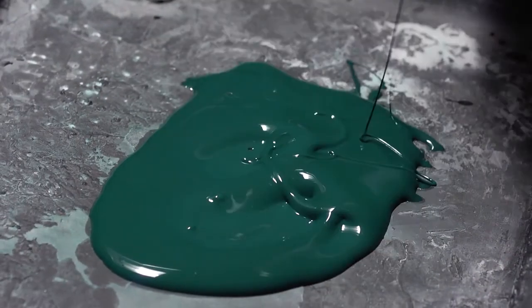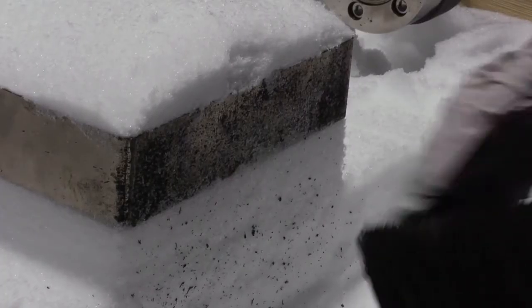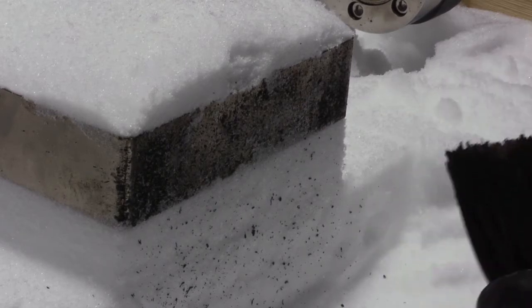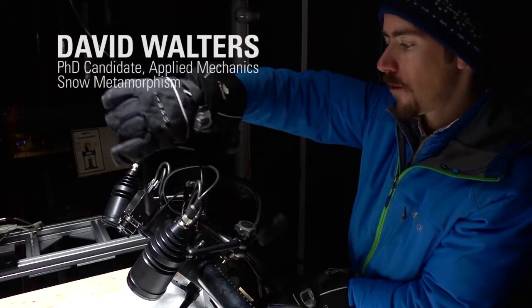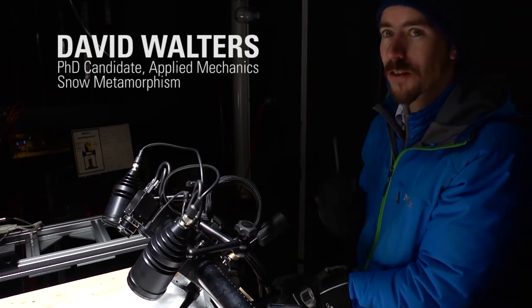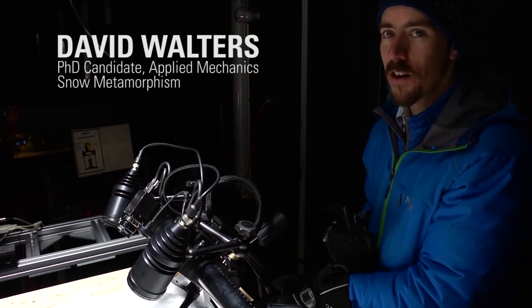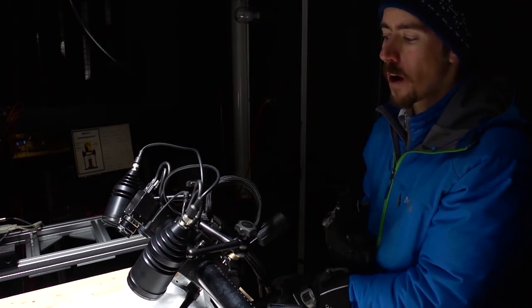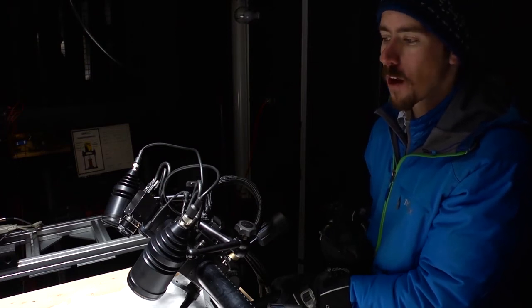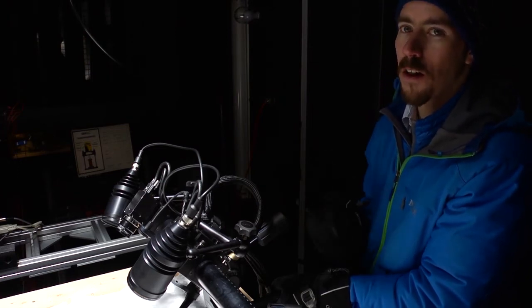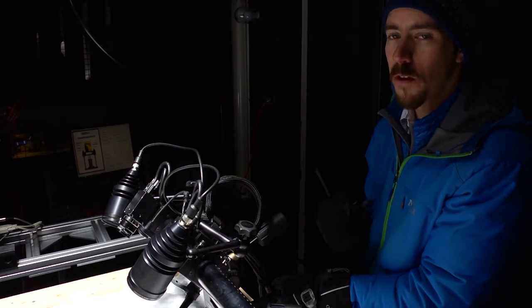So the cameras can identify the pattern in the snow and watch how those individual particles are moving in relation to each other. So we've got two cameras here. They work just like our eyes. It can see in 3D. And these cameras, combined with a really powerful software algorithm, can track that paint pattern and tell us exactly how the snow is moving to pretty fine resolution.